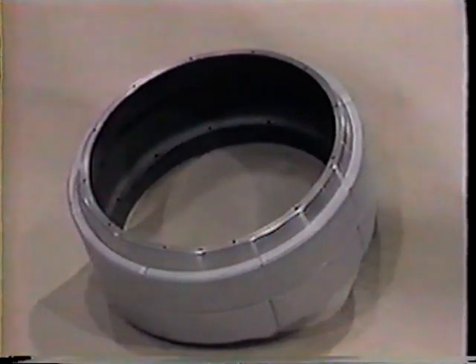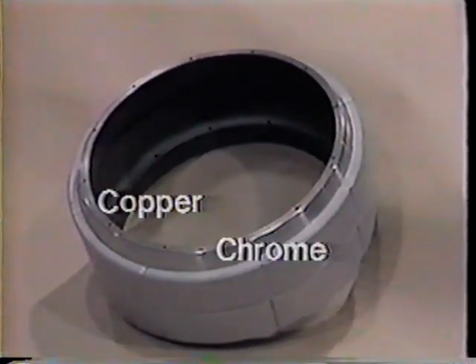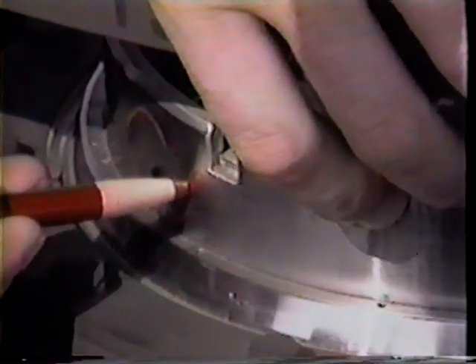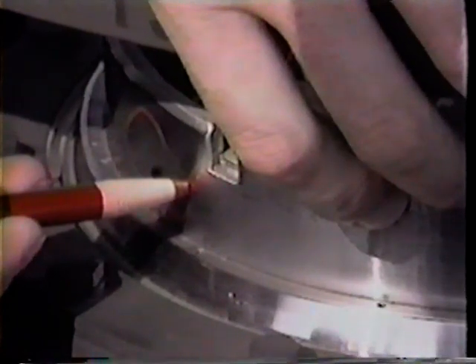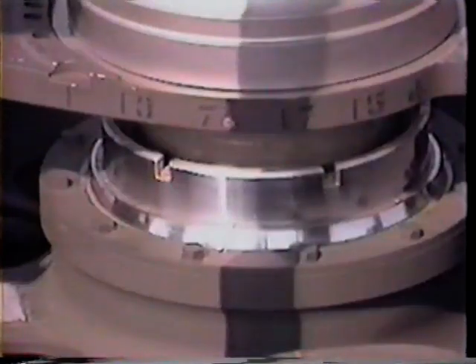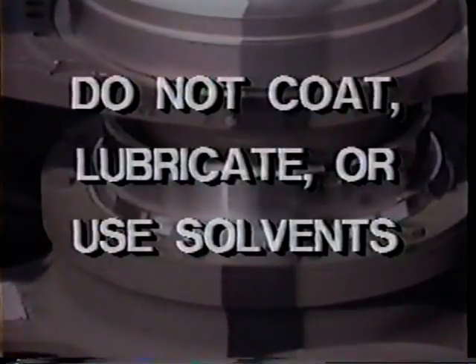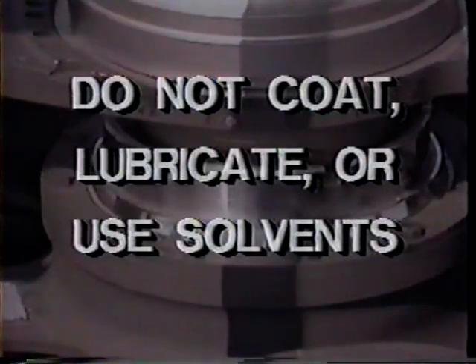Uniballs are now being made with a copper layer below the chrome. Copper doesn't react as much with the chrome. Therefore, it holds the chrome plate better than aluminum. If corrosion, blistering, cracking, or flaking is found in the bearing area during your inspection, check it against the criteria called out in the TM. Replace as required. As with spherical bearings, do not coat, lubricate, or use solvents to clean. For routine maintenance, wash frequently with fresh water.